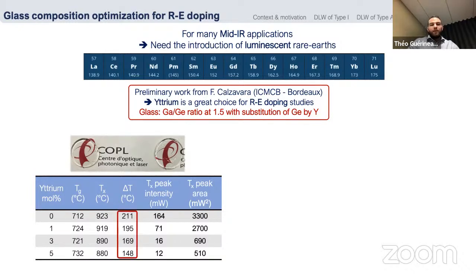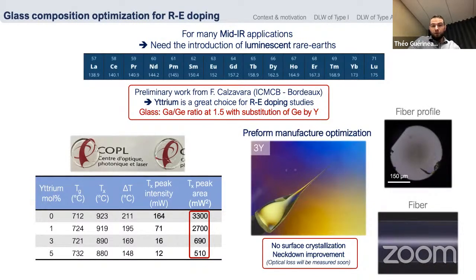At first we could say, okay, the glass is less and less stable. As you can see here, the delta T, the difference between the Tx and the Tg, is decreasing. But when we look at the Tx peak intensity and peak area, you will see that there is 1 order of magnitude difference for this value. So actually, the crystallization of these glasses is less and less spontaneous and slower. So we fiber drew the glasses with 3% of yttrium. We get an improvement of our neck down, and there is no surface crystallization. It's a very good sign for further work on these glasses. Here you have also the fiber profile and a section of our fiber. Since these results are recent, we are not able for now to measure the optical losses.